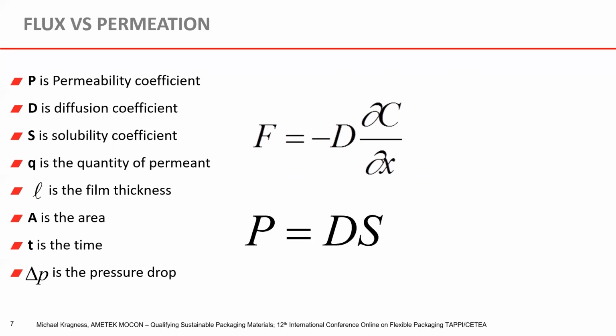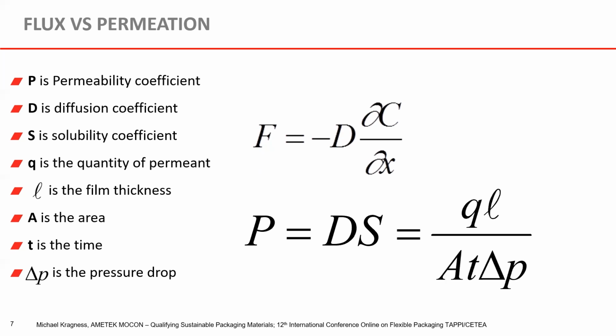To go a step further, we know that permeation is the product of the diffusion coefficient and the solubility coefficient. If you look at this last equation, that is what permeation is: you have the quantity of some permeant, normalized to the thickness, over some area, per some amount of time, per some pressure drop. That pressure drop is across the membrane that the species is permeating across.